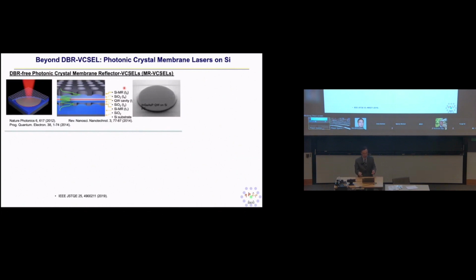The first one is a VCSEL structure, where instead of a DBR structure growth, we can now form this three-layer VCSEL structure without a DBR. In this case, we have a single layer photonic crystal mirror on silicon SOI. We transfer a III-V membrane thin layer structure on top, and then we release transfer another top mirror silicon reflector with a single layer photonic crystal structure on top to form this tri-layer sandwich structure. And this forms a basic VCSEL structure where your FP cavity resonance is formed by two reflectors of single layer photonic crystal structure. So here, just use the schematic and then some of the images we have here.